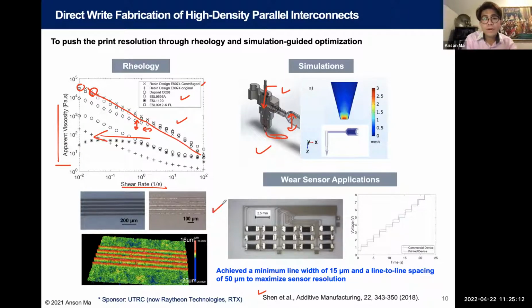But back then, by doing the rheology and also the different print experiments, the key thing here is we managed to get down to very thin lines. So we're talking about 15 microns. Just to give you a sense, your hair diameter is about 100 microns, so this is an order of magnitude smaller. And then also the line-to-line spacing is very, very small. Now, you may ask, why the heck do you want to have high resolution printing? So this is the justification for that.